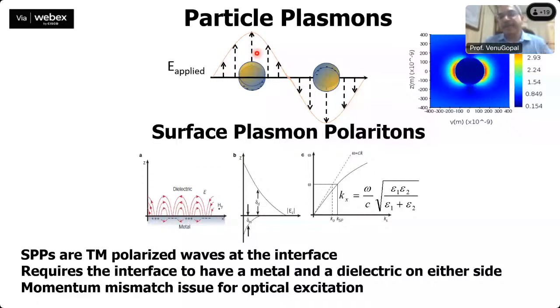Right? Now, we have the diffraction limit, which says that the scattering object should be of the dimension of lambda by 2 or bigger. But now, because of these plasmon resonances, we are coupling electromagnetic radiation to these localized plasmon resonances, where the electromagnetic field from light is converted to the plasmon mode, and then it is confined to dimensions much smaller than the wavelength of light. So we are beating the diffraction limit and taking light to subdiffraction dimensions.